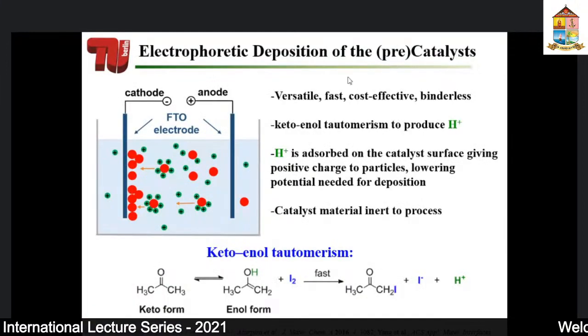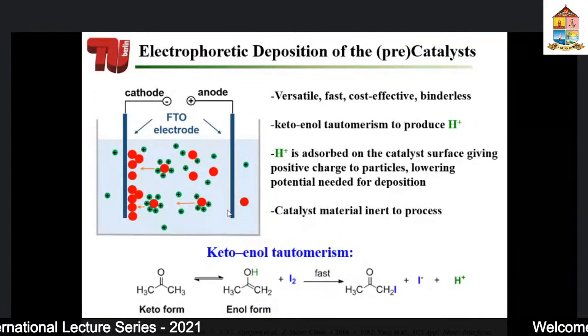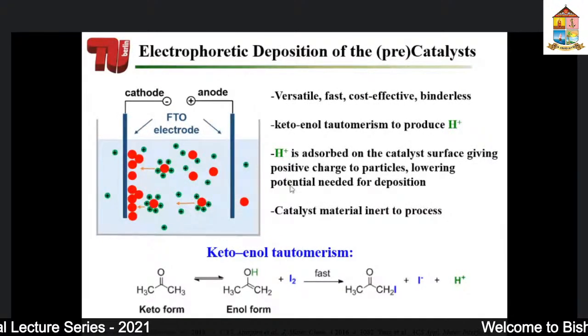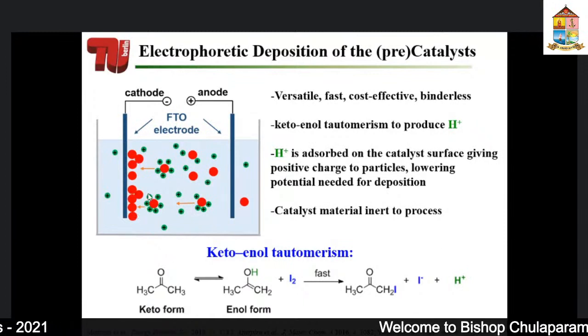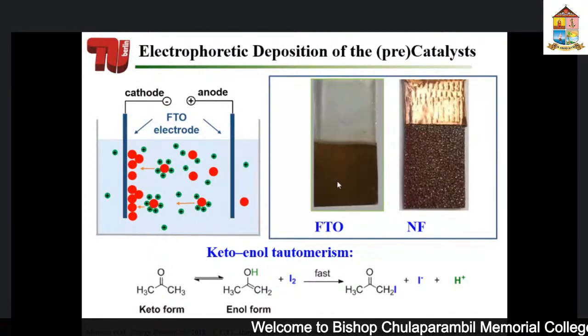So what you could do, you can take your particles, you can disperse them in, let's say, acetone, and you can add some iodine, which forms a keto-enol tautomerism, and which produces free protons. These protons would be absorbed on the particle, and if you apply a potential, they will be migrated towards either anode or cathode, depending on what potential you apply. And then you get very nice films as shown here. I think it's a film of cobalt oxide. As you could see, you can get a very nice, highly dispersed film.